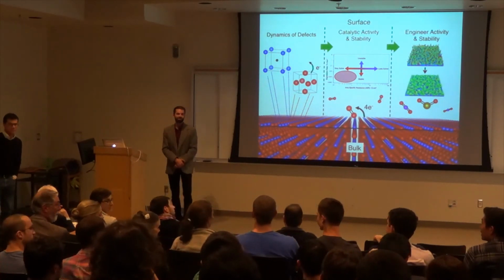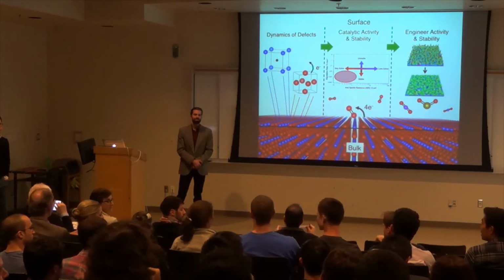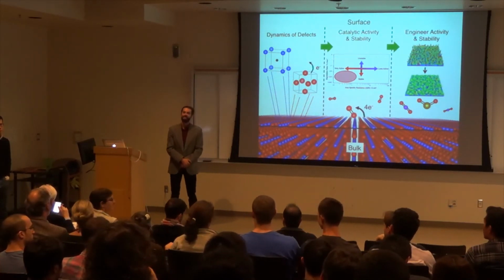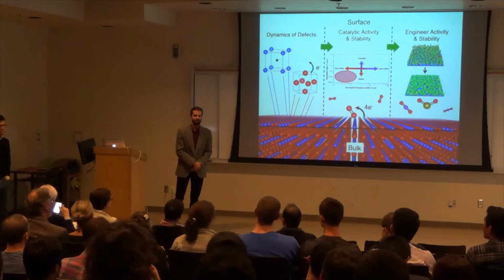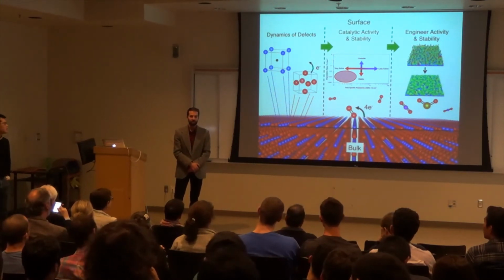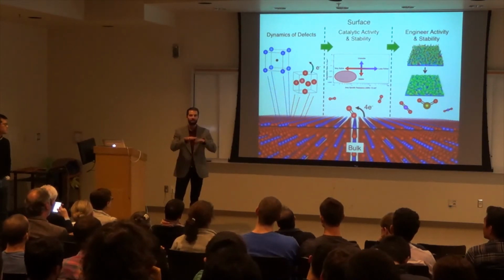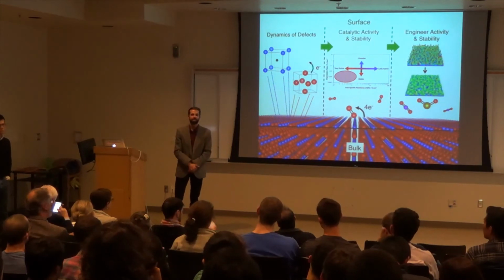Maybe I missed it, but what technique do you use to deposit your films? Yeah, I didn't mention this. Pulsed laser deposition. So it allows you to deposit the films at high temperatures, like very dense, thick films, very controllably.